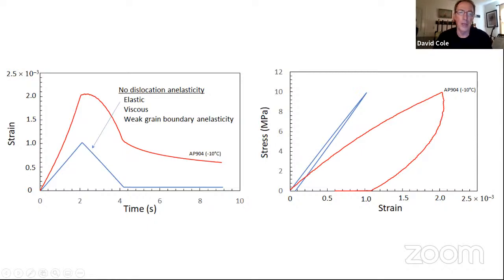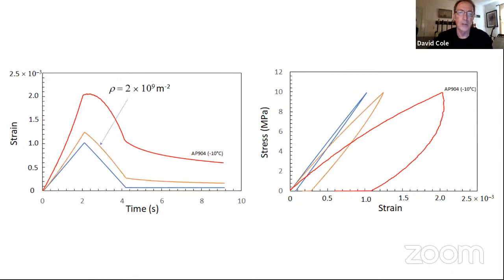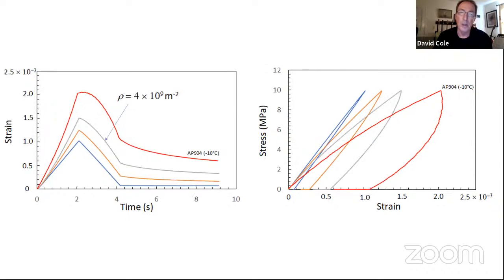So let's introduce dislocations, but a low dislocation density, 2×10⁹ per square meter. We'll get into what that really means later on. So now we're calculating a low dislocation density response. We see we're a bit off the original elastic curve, but we're not there yet. The only thing I'm doing in these calculations is increasing that one quantity, the dislocation density. Let's double it again to 4×10⁹ per square meter. We're getting better.